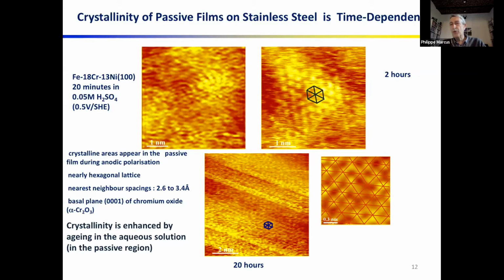And we have shown in some other works that the time of exposure in the passive region provides better resistance to localized corrosion in chloride solution. And this is due in part to the enhanced crystallinity that is demonstrated on this slide. The other factor being the enrichment of the passive layer with chromium.